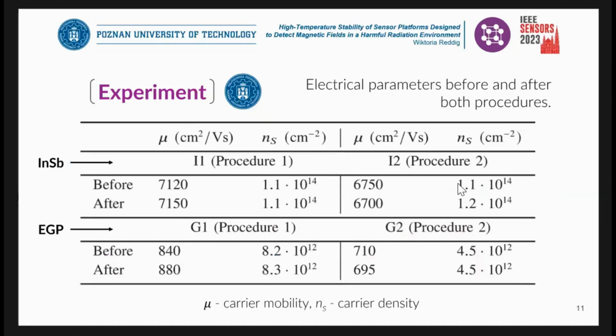Here we have gathered results of every measured sample, every sensor, before and after every procedure. And in general, the changes are really minimal. None of these changes exceed 5%. In terms of the first procedure, the graphene experienced this 5% change. The indium antimonide one experienced like 1% change, so it is really good stability.